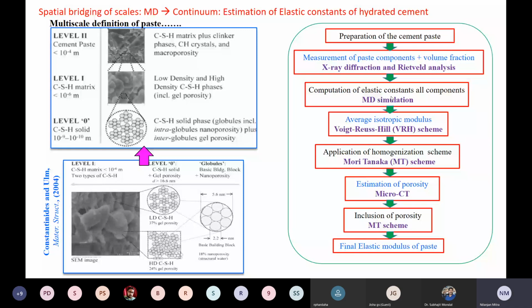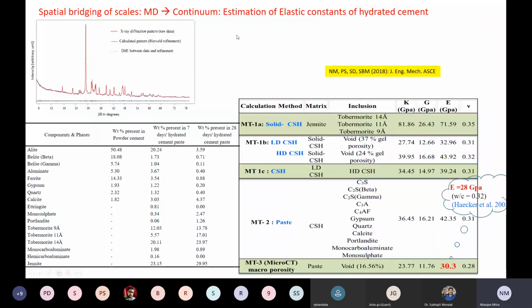Anyway, so yes, here you see how your XRD looks like. You have different peaks, and these different peaks correspond to different things. In this case, for the constituents of the cement paste, you have all different phases. You can see 16 different phases in there. This is what is there in the powdered cement. So powdered cement will have alite, belite, aluminate, ferrite. All of them have obviously different types of chemical formulas. What I showed you, C3A, that is basically aluminate. Okay. And gypsum I also showed you.